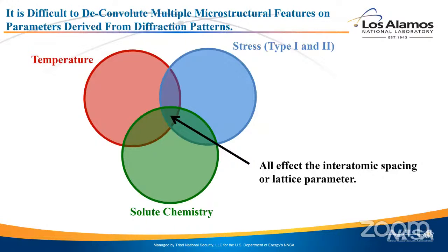Because there are a lot of things that can change it. Certainly temperature, right? If you're doing annealing in situ, you raise the temperature, that changes the spacing between atoms. It'll also change the solute chemistry, and the solute chemistry changes the spacing between atoms. Stress will change the spacing between atoms, right? If you squeeze something, the atoms get closer together. That makes sense. And that even has sub-areas that are convoluted within it. You have type 1, type 2, and type 3 stresses: macroscopic stresses, intergranular stresses, and intragranular stresses. Those all affect the atomic spacing. So how do you deconvolute all those effects out of the diffraction pattern? That is a lot of what I'll talk about today.